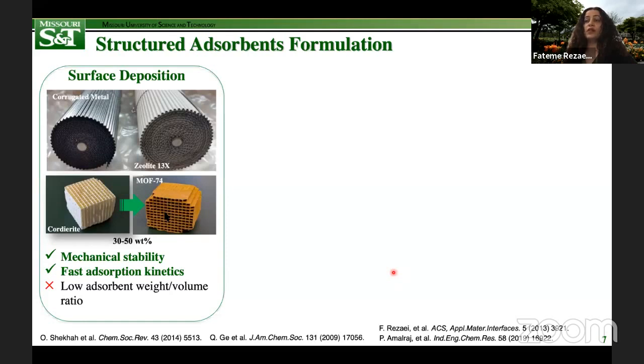The active adsorbent may be deposited on the walls of a substrate, such as monoliths or hollow fibers. This approach has been extensively studied to deposit thin films of zeolites or MOFs on the substrates, with two examples shown here: deposition of 13X zeolite on a corrugated metal foil and MOF 74 on a cordierite substrate.